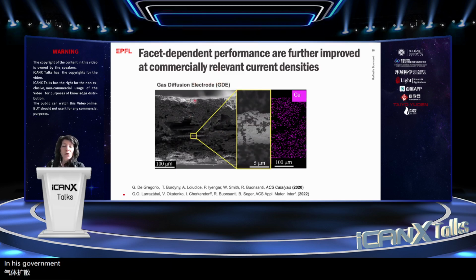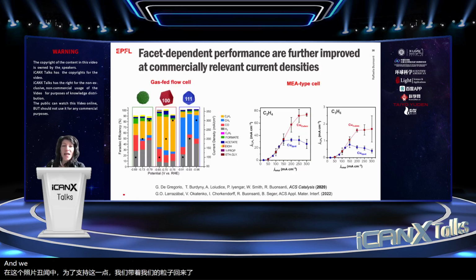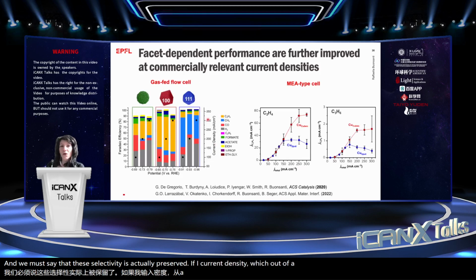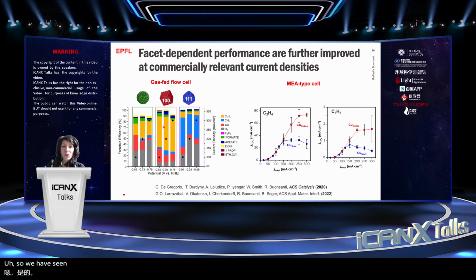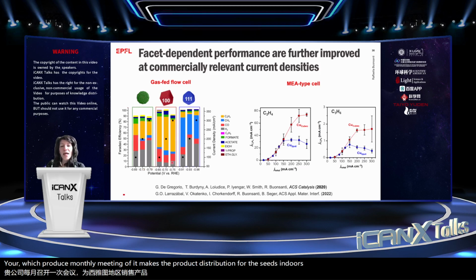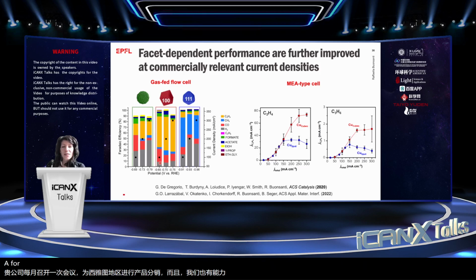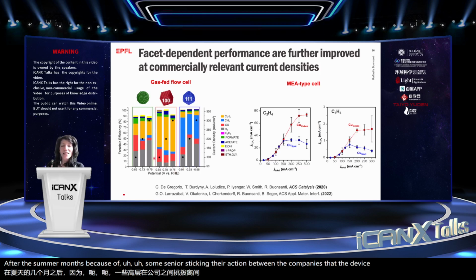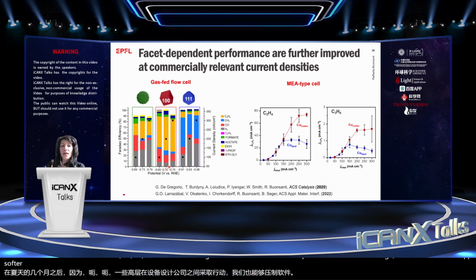In this gas diffusion electrode, we have a porous carbon support, and in this porous carbon support, we can deposit our particles and demonstrate that this selectivity is actually preserved at high current densities, which are commercially relevant, like 300 milliampere per centimeter square. So we still have the cubes, which produce mostly ethylene, the octahedra, which produce mostly methane, a mixed product distribution for the spheres. And because of some synergistic interaction between the catalyst and the device design, we're also able to suppress further hydrogen.